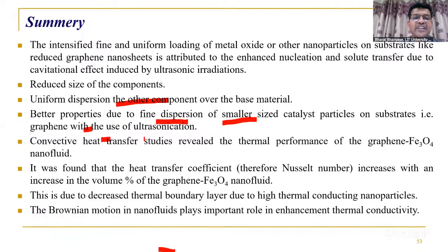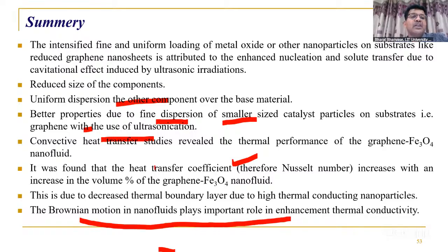Convective heat transfer studies reveal thermal performance of graphene Fe3O4 nanofluid. We found improved heat transfer coefficient, that is Nusselt number, and that is because of improved thermal conductivity due to Brownian motion in the nanofluid.